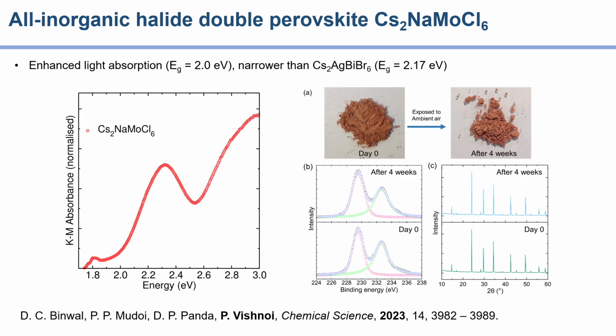And this 3D material, if I compare the band gap with the key double perovskites which are useful for optoelectronics, this is one of the champion materials, because as I mentioned, the iodide is not known. So the material with the narrowest band gap known is the bromide. Compared with this, we have this material with a slightly narrower band gap, and it is very stable for a month or so under ambient conditions, considering that molybdenum 3+ is actually vulnerable to ambient oxidation. But still, it seems that in these kinds of lattices, molybdenum 3+ remains stable for long, irrespective of whether it is 3D or 1D.